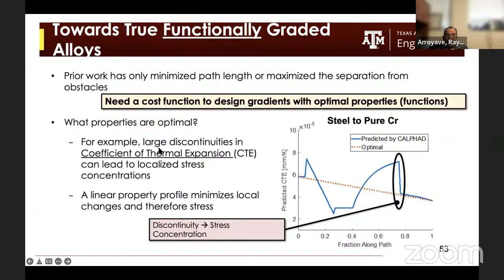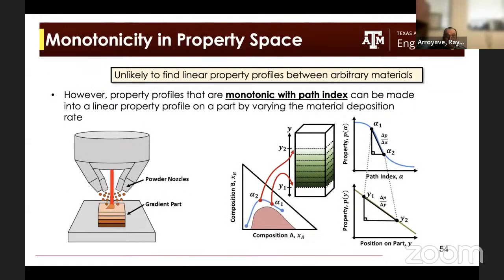For example, large discontinuities in the thermal expansion coefficient could lead to significant stress concentrations, right? So a property profile that is smooth may actually minimize these changes, and therefore the stresses that are built up when the material is subject to temperature changes. And that is just one example. We could actually grade on purpose other types of properties, such as strength, or elastic modulus, or other types of properties for different applications.